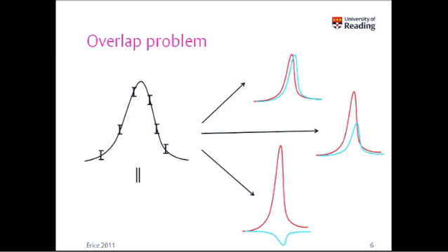And when you come to do the profile fit, which is basically a model-free fit to the data, to fit the profile and estimate the reflection intensities, you find that there's no reason why this solution, where we have two basically equipartitioned intensities, or this solution where they're split roughly 75-25, or even this solution where we have a very strong peak correlated with a peak with negative intensity, there's absolutely no reason why those can't fit to within experimental error. And you find that when you do the profile fit, very often you will get areas such as this where we have a strong positive correlating with a strong negative. However, if you do the fit correctly and you preserve the correlation matrix that comes out of the least squares fit, then it really doesn't matter what the individual intensities are, because it will always sum back up to give us the net intensity of the observation.